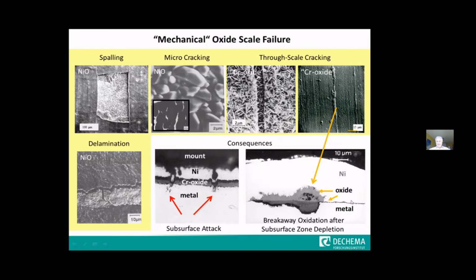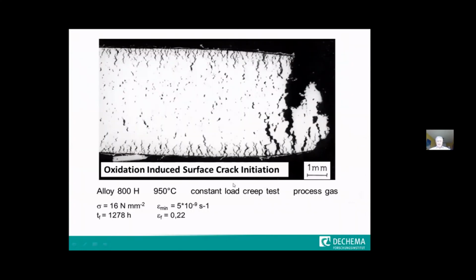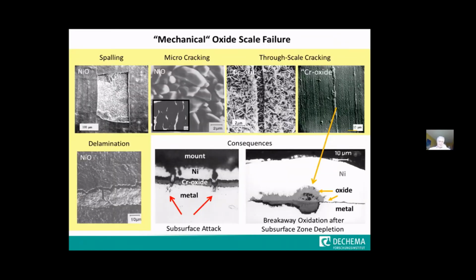So here, this was the thin oxide layer in the cross section, and after breakaway, such a thick oxide can be formed, which means that no longer the same protective situation exists. Another interesting slide is this one. You can see an oxide scale in the cross section, and where there are cracks, the subsurface attack starts and the damage starts. This is a good proof that we need protection by such an oxide scale, which must be defect-free, non-damaged, and must have a good protective effect against the environment, which would be out here.